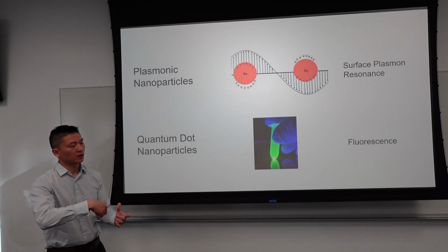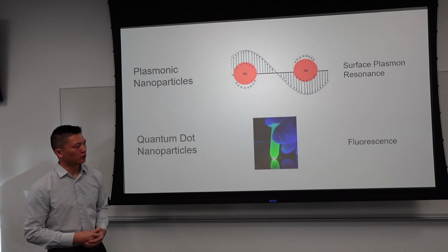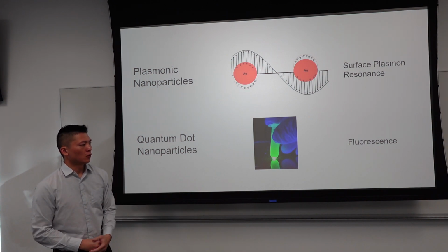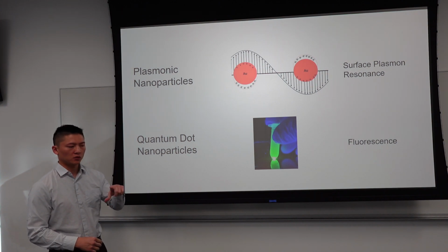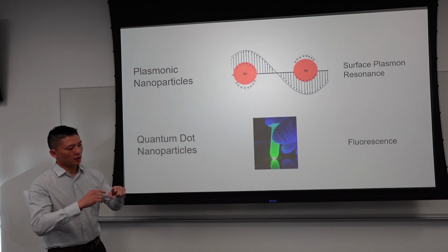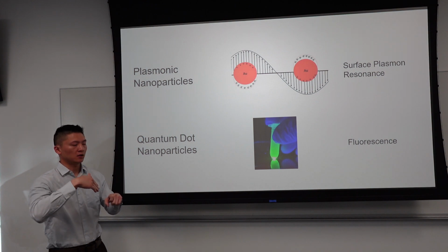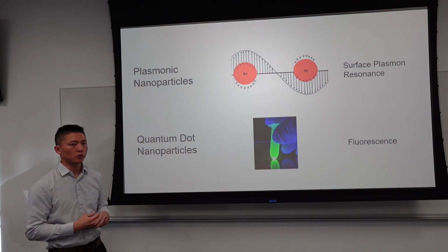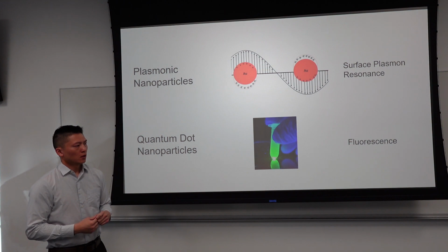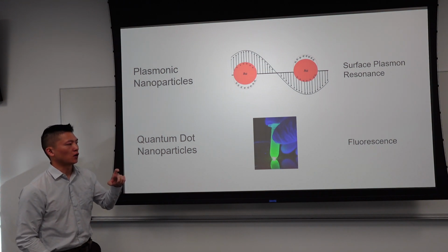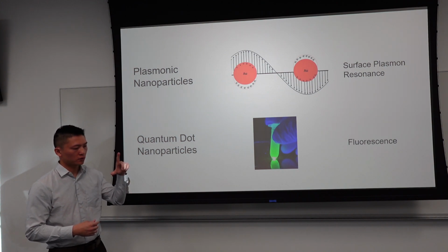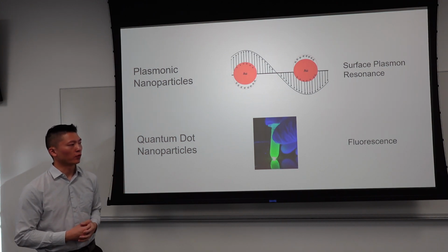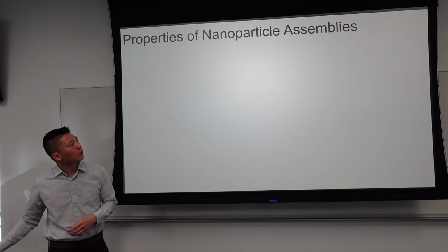Essentially, we can excite the electron with UV. Here, a UV lamp is shining upon, or illuminating, this sample, and because of the quantum confinement within a nanoparticle, an electron can be excited into discrete states. It behaves similarly to atoms. Of course, it leaves a hole, so this exciton is created. And upon relaxation, it may refluoresce.